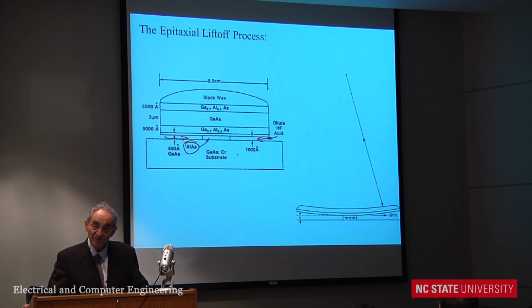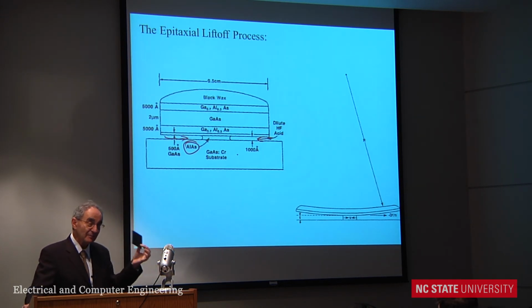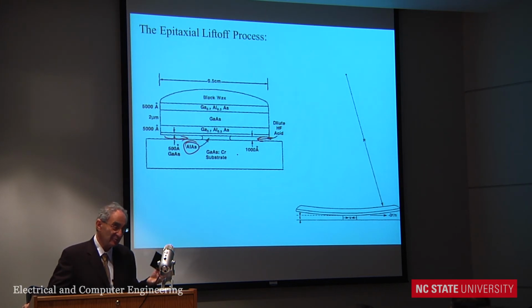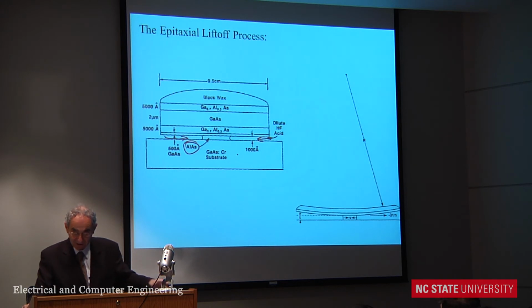You're going to reuse the substrate over and over again, and you're only using the amount of gallium arsenide you need, which could someday be as little as 100 nanometers worth or 60 nanometers worth. So it's an insignificant amount of gallium arsenide that you end up using. And it's due to the direct band gap and the light trapping together. You'll end up using very, very little.